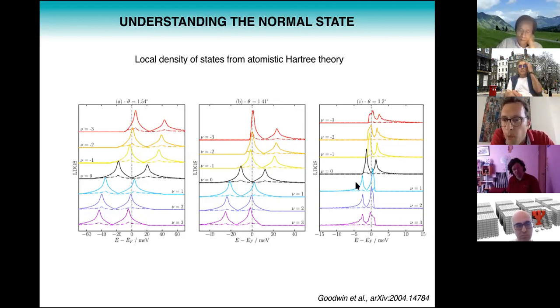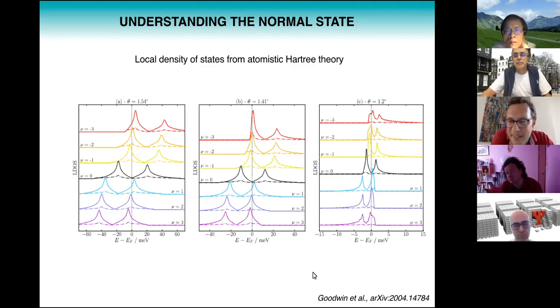And again, that gets even more pronounced when you go very close to the magic angle. You see strong asymmetries, strong Fermi level pinnings, and you start to see some very strange shapes in the local density of states. So the Van Hove singularities acquire some definite structure, and sometimes the structure looks a lot like a double peak. This raises some questions about the interpretation of the experiment, where this double peak was interpreted as a signature of a broken symmetry. But here I'm showing you that even in the normal state, the Van Hove singularity can acquire non-trivial structure in the vicinity of the magic angle.